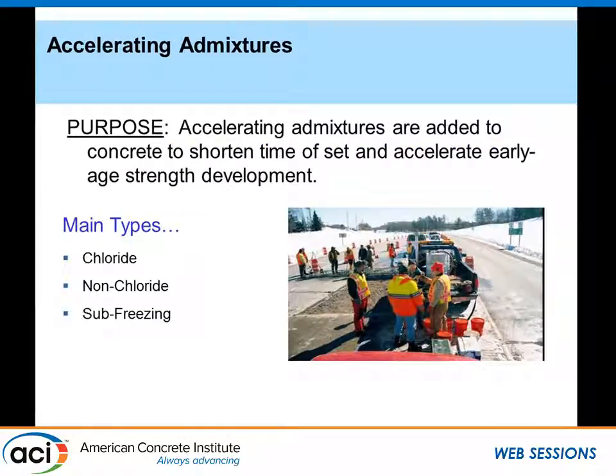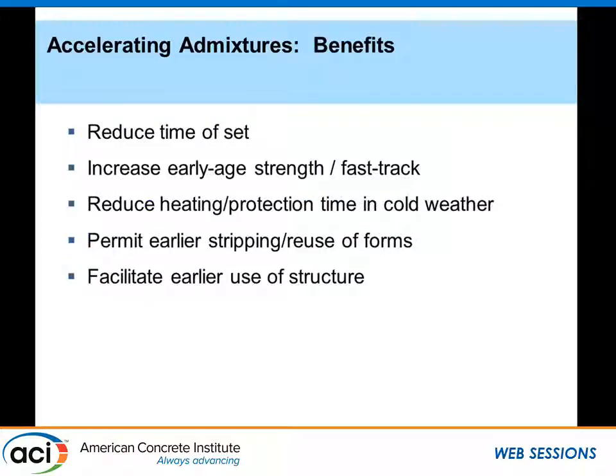Accelerating admixtures are time-of-set products used in winter. Their main purpose is to shorten the time of set and accelerate early age strength development. Main types are chloride and non-chloride — for reinforced or prestressed concrete, non-chloride materials must be used due to the corrosion risk from chlorides. Benefits include reducing time of set, increasing early age strength for fast-track applications such as overnight pavement replacement, reducing heating and protection time in cold weather, permitting earlier form stripping, and facilitating earlier use of a structure.